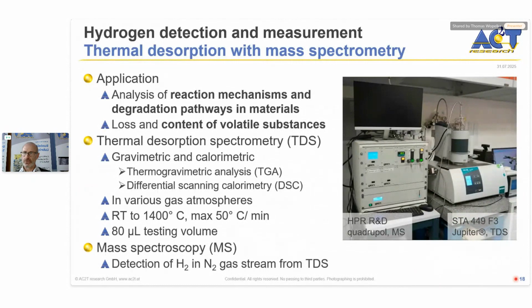And the last equipment I want to show is this thermal desorption spectrometry. The application is the analysis of reaction mechanisms, degradation mechanisms of the samples you investigate, or the loss of content of volatile substances. In principle, it's a chamber where you put your sample. This chamber can be heated up to 1400 degrees Celsius. And the chamber is equipped with a very accurate scale with high resolution, and you measure with thermogravimetric analysis the weight loss of the sample on this scale.